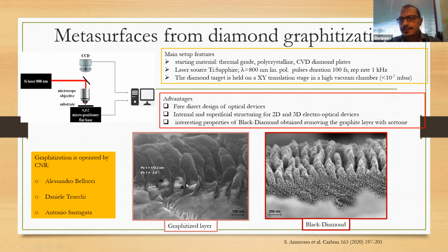We have also studied the structure that is obtained by removing this graphitized layer. When we remove this graphite from the top, we have what we have called the black diamond, because the sample is always black, but of course for optical reasons. We can see that underneath, these ripples are now made just of diamond and are on a nanoscale. But even in the terahertz scale, we can measure the change due to the dichroic properties now provided by these ripples.